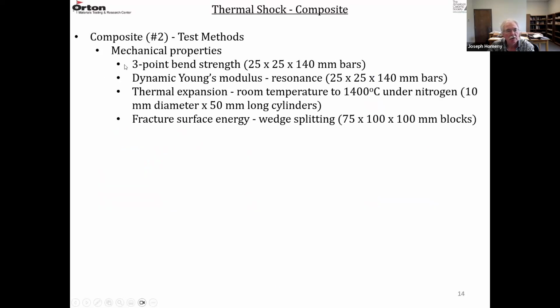So they measured bend strength in three-point bending, and dynamic Young's modulus by the resonance technique. These were both done on 25 by 25 by 140 millimeter bars. Thermal expansion was measured from room temperature to 1400 degrees C, and that has to be done in an inert atmosphere like nitrogen. These were 10 millimeter diameter by 50 millimeter long cylinders. And then the fracture surface energy was measured with the wedge splitting test with the normal size block, 75 by 100 by 100 millimeters.